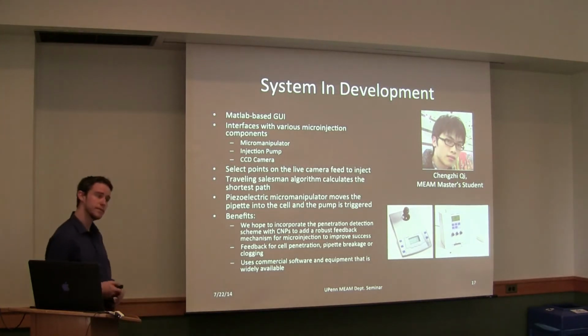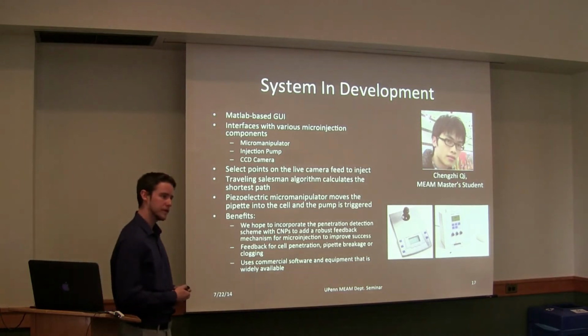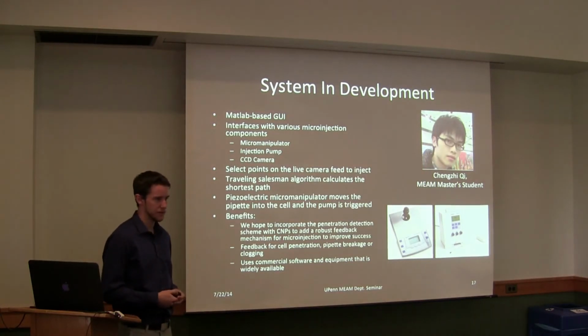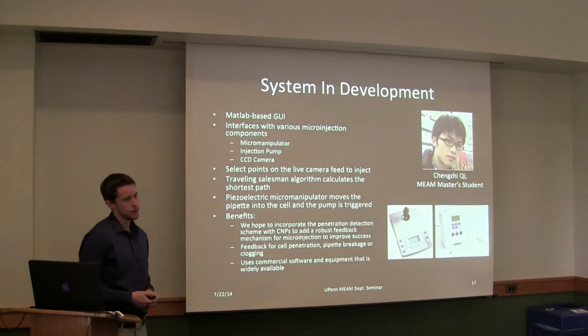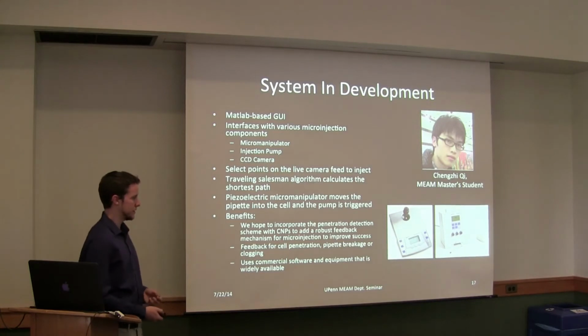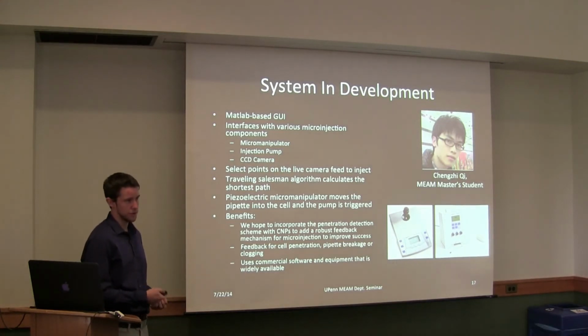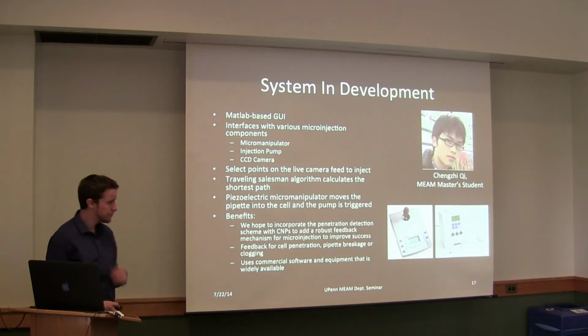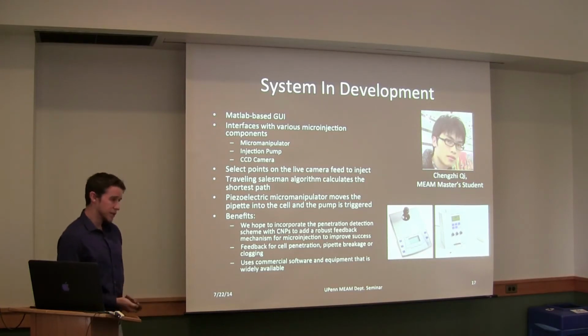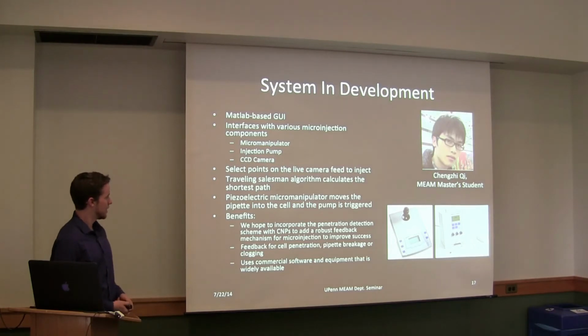So the benefits, yeah. Controlling flow rate or pressure? The pump is pressure controlled. Yeah, so at this scale the flow rate is linear with the pressure. The tip is nanoscale, so the flow through the tip is still going to be in the laminar regime. So we typically use pressure. You can adjust the injection time, so if you want to double the amount you're injecting, you can either double the pressure or double the injection time to compensate.